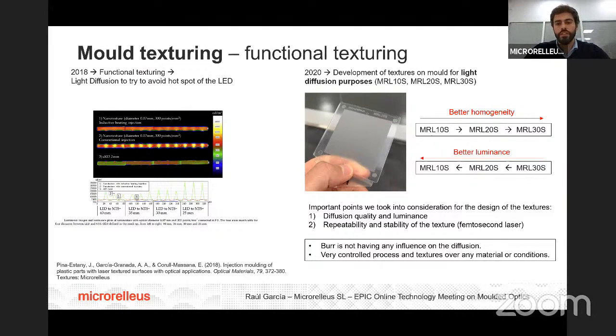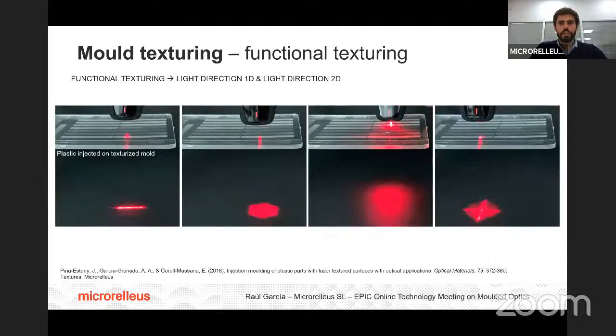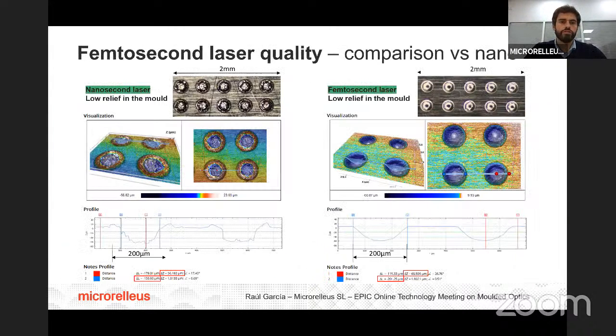Burr has no influence on the diffusion, so it is a very controlled process, with textures over any material and conditions. Here we can see diffusion in one direction, two directions, or the homogeneous one. And here we can see a comparison between the nanosecond laser and the femtosecond laser.